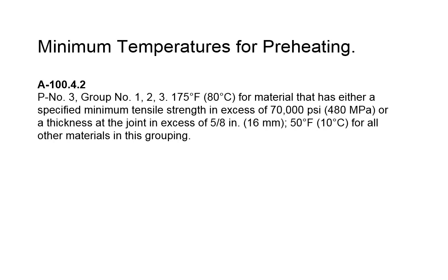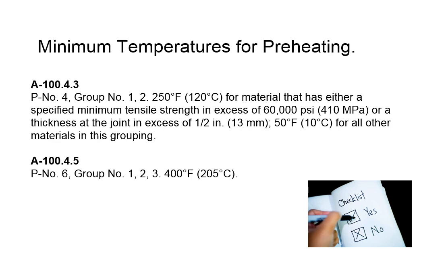So if it's in excess of 70,000 psi, you got to go to 175. Or if the thickness of the material is 5/8 of an inch or greater, you go to 175. For everything else, you just go to 50. So you can see as we're going through this, we're getting a little more difficult to deal with. P4 materials, you've got 250 for anything where the tensile strength is in excess of 60,000, or the thickness of the joint is in excess of half an inch. So you can see as we're ratcheting it up here, P3, P4, those materials all need a preheat.